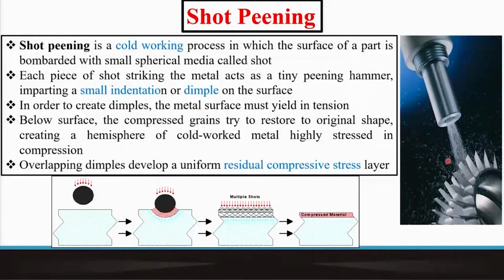But these spherical objects that we are talking about are actually not as big as this. They are actually pretty small, 0.5 millimeter, 0.6 millimeter, or even less. And they're made out of steel, high alloy steel. Obviously, then the density is higher. At times, they could also be of alumina or zirconia, such spherical ceramic oxides, which have very high elastic modulus, apart from, of course, being able to deliver the right kind of impact energy.